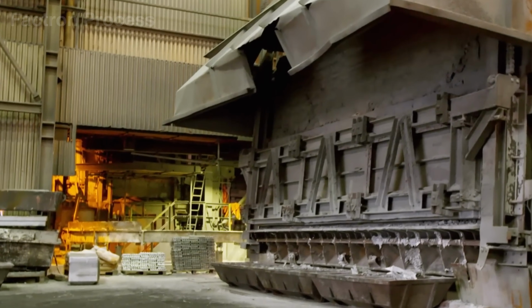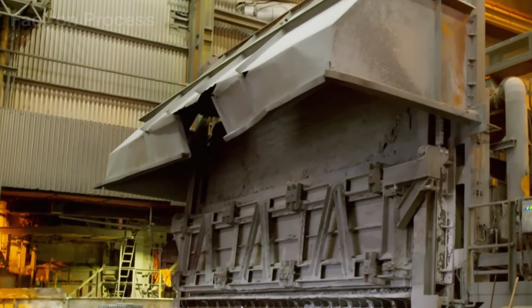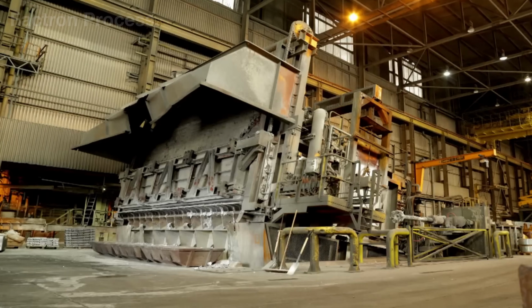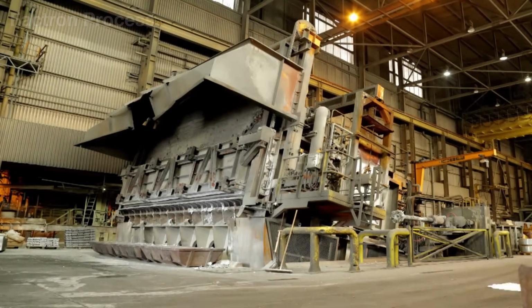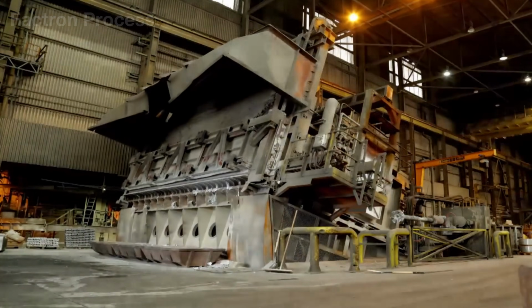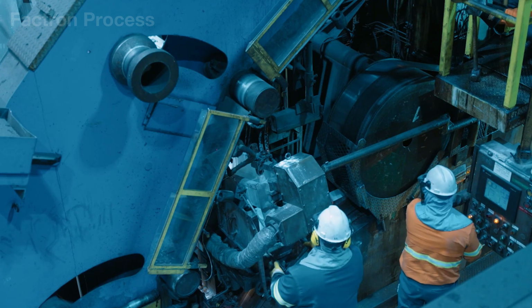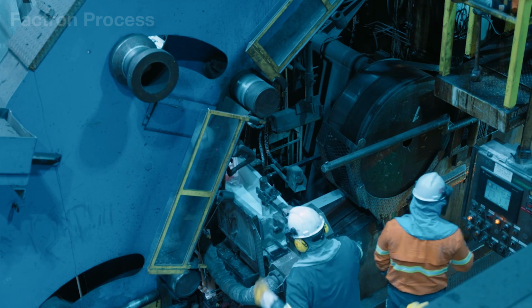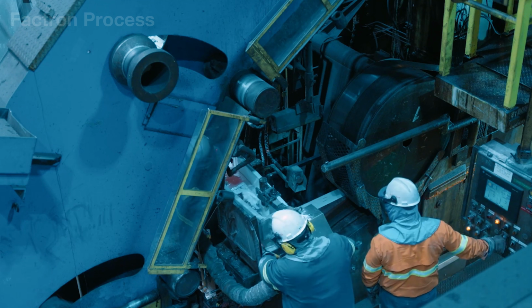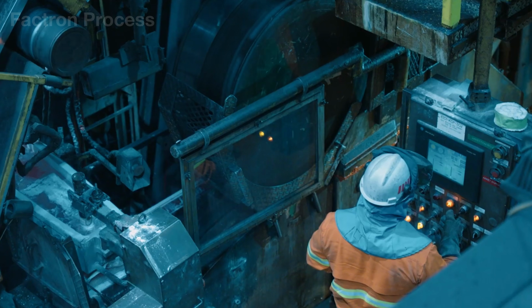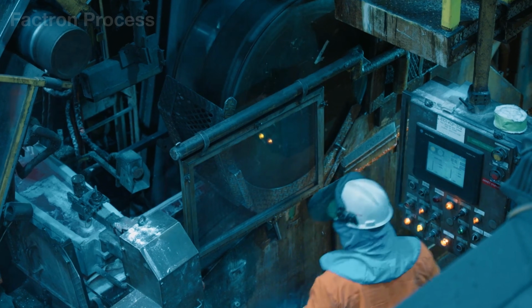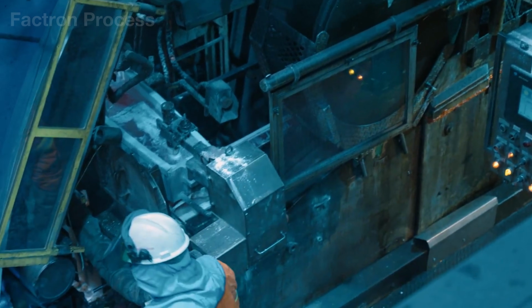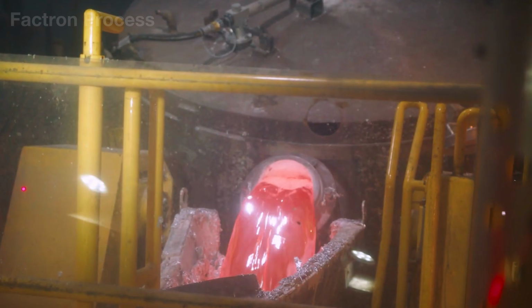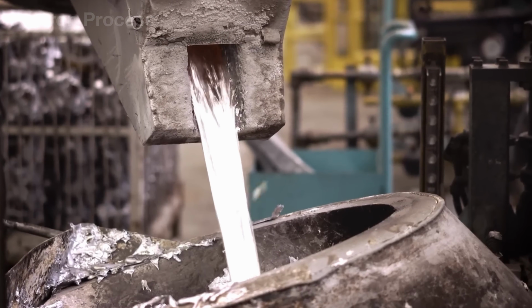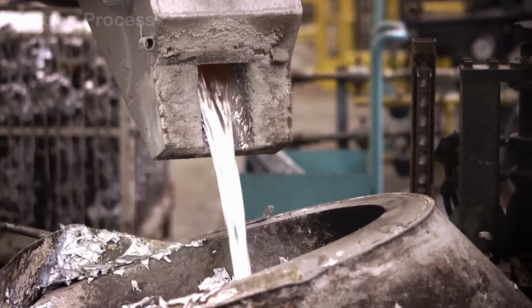Once the molten metal meets the required specifications, the holding furnace carrying tens of tons of aluminum slowly begins to tilt. A brilliant white stream of molten metal pours from the furnace, flows through heat-resistant launders, and enters casting molds positioned above a deep pit. At this stage, the metal flow, furnace angle, and temperature must remain extremely stable, because even a small fluctuation can create cracks, distortion, or internal defects.